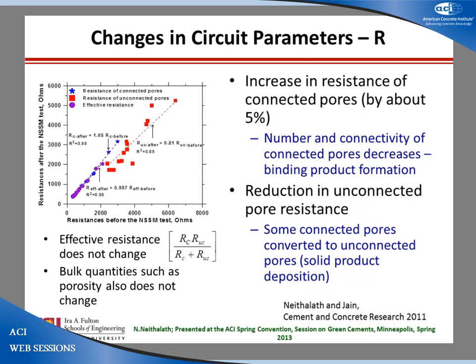So if you look at changes in the resistances, now overall resistance really doesn't change because only very small amounts of chlorides go in. So if you look at the effective resistance before and after, almost no change. But if I break it down into the connected pores and the unconnected pores, you can see the resistance of the connected pores goes up, which means connected pores are becoming more disconnected because you have some products being formed. The unconnected pores, you have to have that balance because this value is roughly the same. The unconnected pore resistance goes down. So the idea is number and connectivity of connected pores decrease.